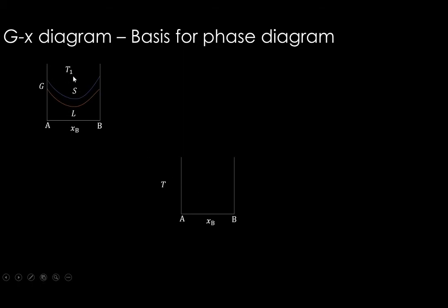Here we have temperature T1, and throughout the composition range, this liquid phase is below. So if you look at Gibbs energy minimization, we don't need to bother about solid at all here. Throughout the entire composition, liquid is the stable state. That's the meaning of it. Even if you draw at each point a tangent and see, you will get in all the points liquid is the stable state, and the entire two curves will be above that tangent for any point. Okay. So liquid is the stable state throughout the composition range at T1. This is the information. Let us map it in the diagram.